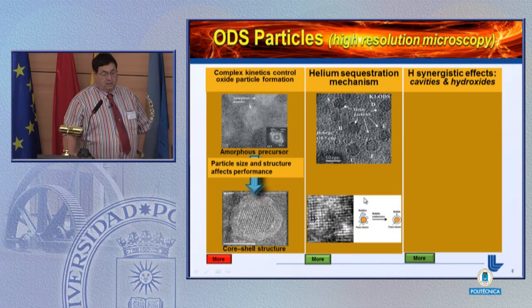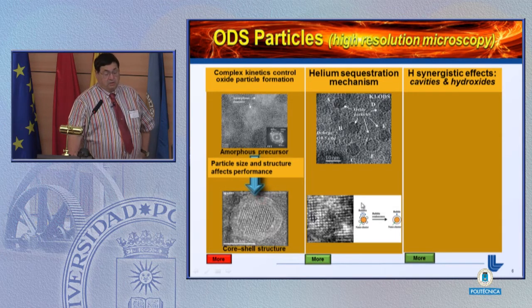But let me talk about the helium sequestration mechanism that's associated with these nanodispersed particles that make up the ODS system. These nanoparticles, which you see here, notice the scale is about 10 nanometers in this TEM micrograph. These are primarily variations of yttrium oxide. The alloy is formed by ball milling or mechanical alloying, followed by consolidation typically at a temperature of about 1050 degrees C.